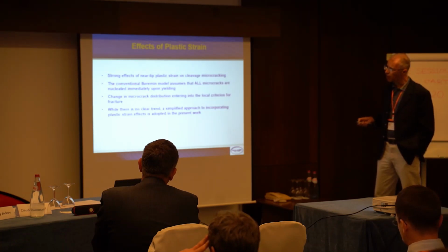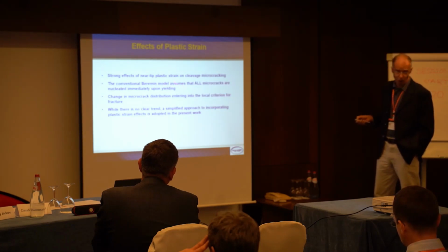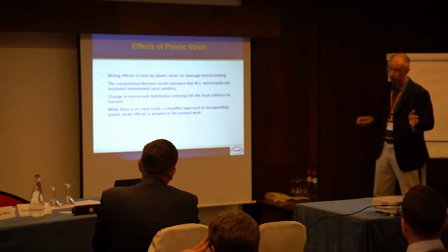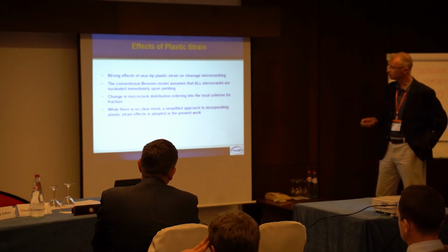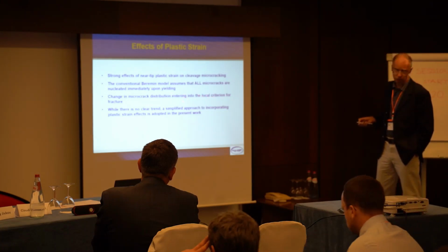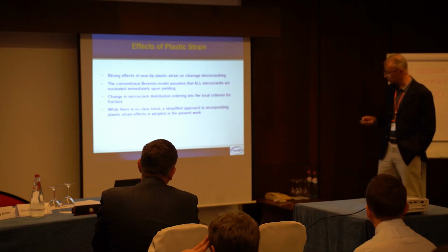And one of the drawbacks of the conventional Beremin model is that it assumes that all microcracks are nucleated immediately upon yielding, which is not true. Microcracks will nucleate as yielding progresses, and this will change the microcrack distribution and also the local criterion. Okay? So we need a simplified approach, and that's what we did.